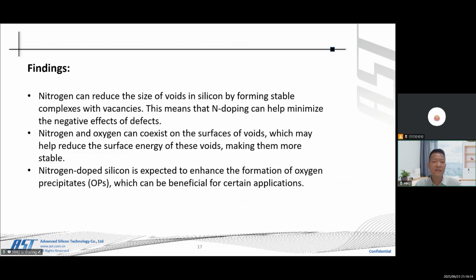These are the findings in our study. Nitrogen can reduce the size of voids in silicon by forming stable complexes with vacancies. This means that nitrogen doping can help minimize the negative effect of defects. Nitrogen and oxygen can coexist on the surfaces of the voids, which may help reduce the surface energy of these voids, making them more stable. Nitrogen-doped silicon is expected to enhance the formation of oxygen precipitates, which can be beneficial for certain applications.